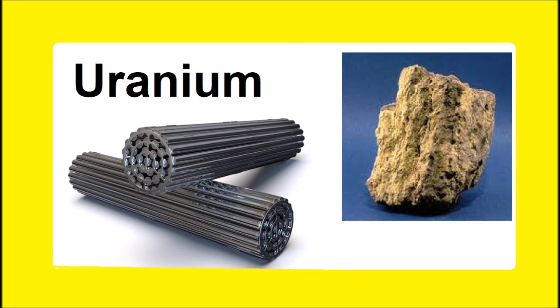A process where green pellets are heated to a high temperature, about 1750 degrees Celsius, in a reducing atmosphere to consolidate and strengthen them. 13. Pellet microstructure. The arrangement and distribution of particles within a UO2 pellet, which affects its performance in a reactor. 14. Burnable absorber. Materials added to fuel pellets to absorb neutrons early in the fuel cycle, such as gadolinium, to manage reactivity. 15. Gadolinium. A chemical element used as a burnable absorber in fuel pellets, allowing higher initial fuel enrichment